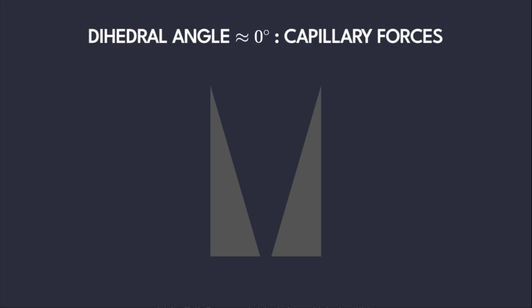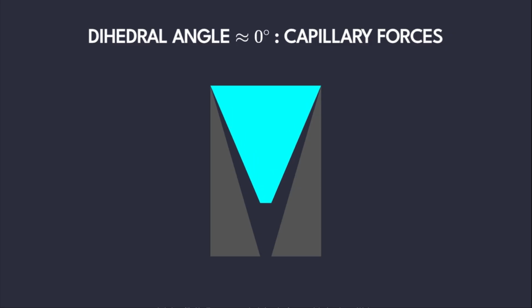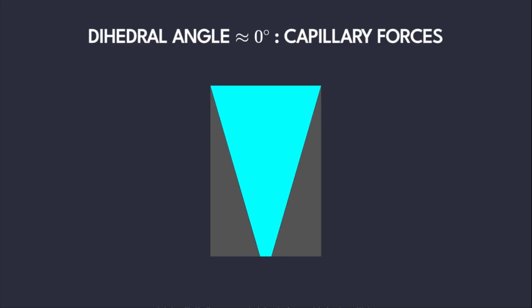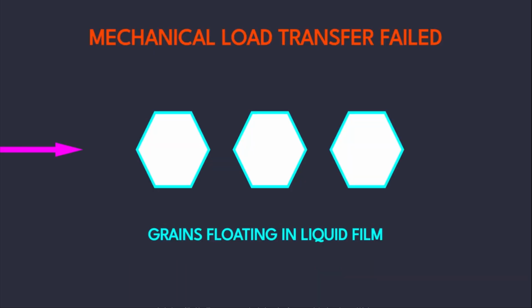The speed at which gallium destroys aluminum is driven by the physics of grain boundary wetting. In metallurgical terms, a liquid is said to wet a boundary if the energy of the liquid-solid interface is less than half the energy of the original grain boundary. Gallium exhibits an exceptionally low dihedral angle when in contact with aluminum grain boundaries, often approaching 0 degrees. This means the liquid gallium is pulled into the metal by capillary forces, much like water being absorbed by a sponge. This movement occurs at speeds far exceeding standard bulk diffusion. In some aluminum alloys, gallium can migrate through the material at rates of several millimeters per hour.